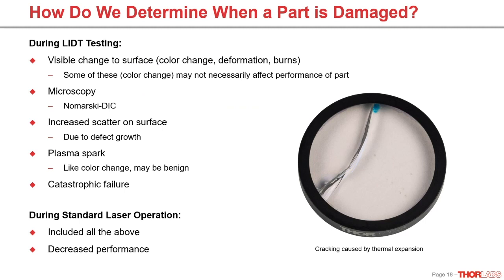One of the questions we often get is, how do we determine when a part is damaged? Well, in something like this, you can pretty plainly see there's a large crack in the optic, and you can see the optic is cemented in a ring. So as the glass is heated, it's going to expand, and in this case, it's bounded. So something has to give, and in that case, that's the glass here.